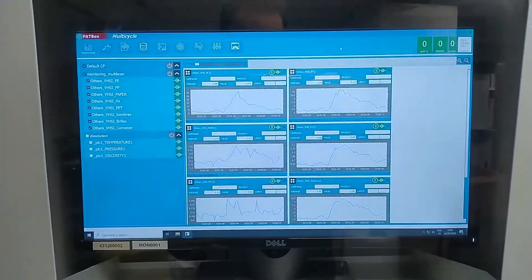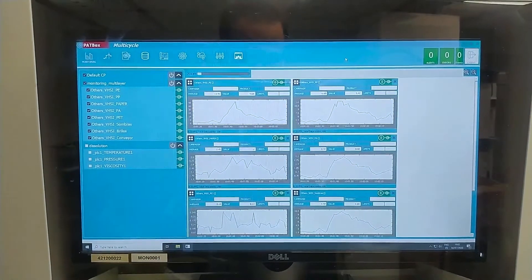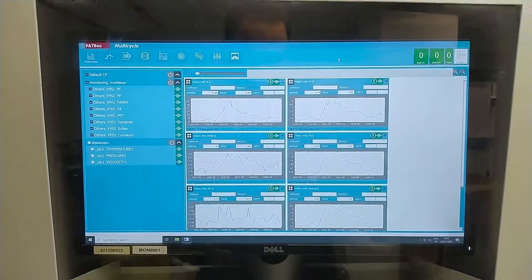The complex spectral information obtained from either near-infrared hyperspectral imaging for flexible packaging waste, or laser-induced breakdown spectroscopy for composites, is interpreted by the process control software to determine the best strategy for recovery of target materials.